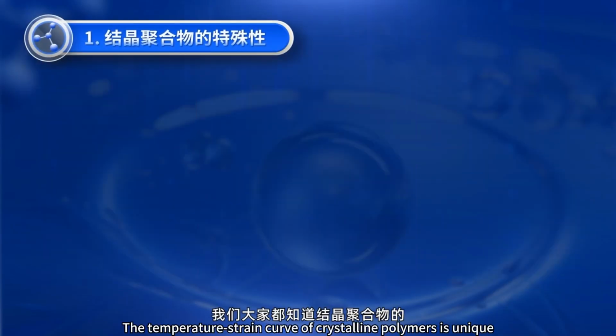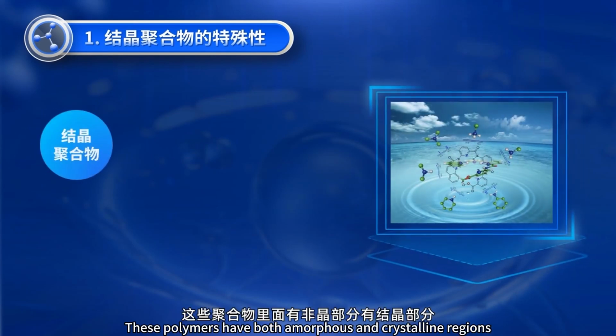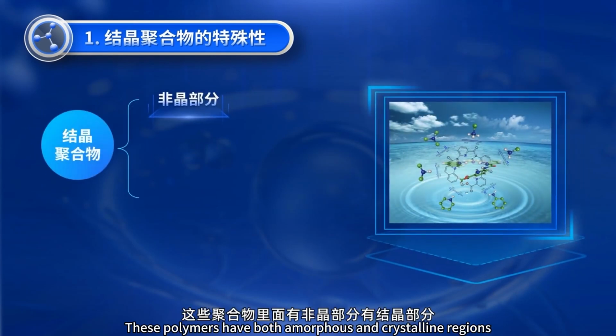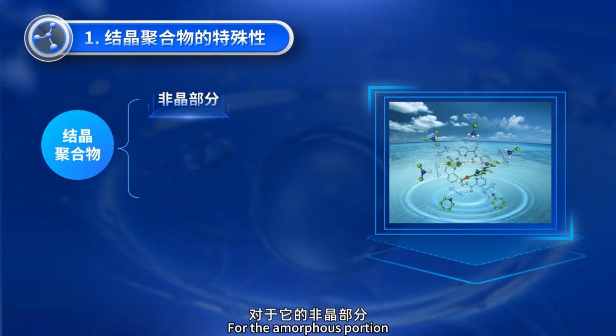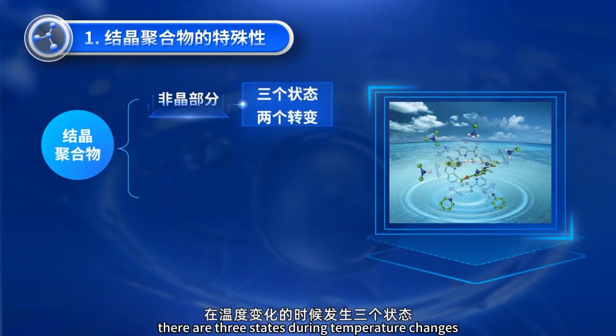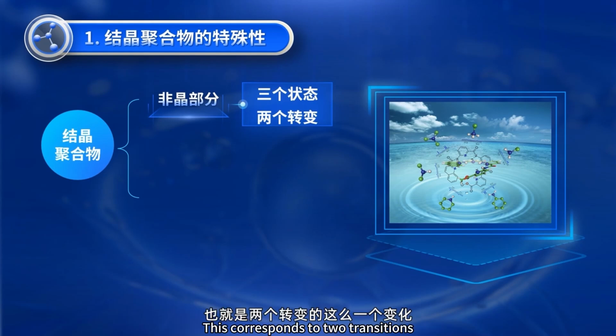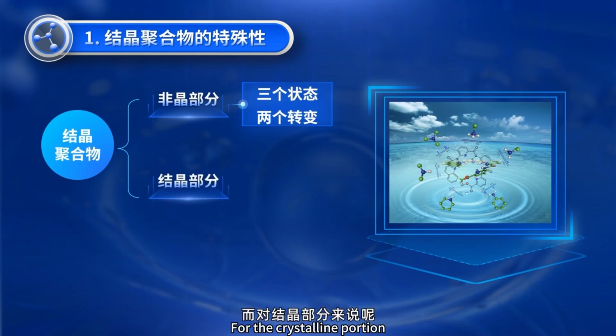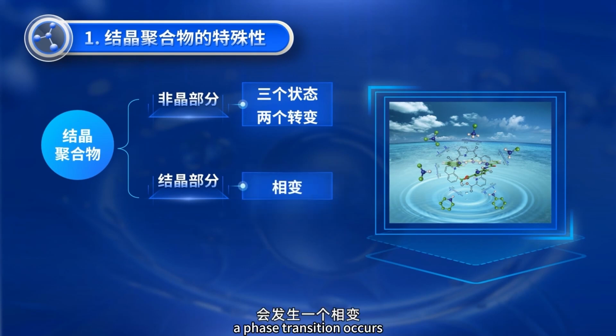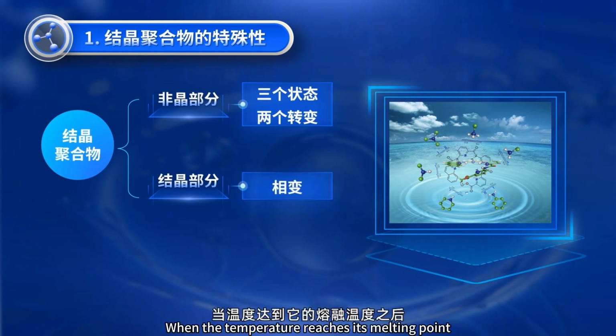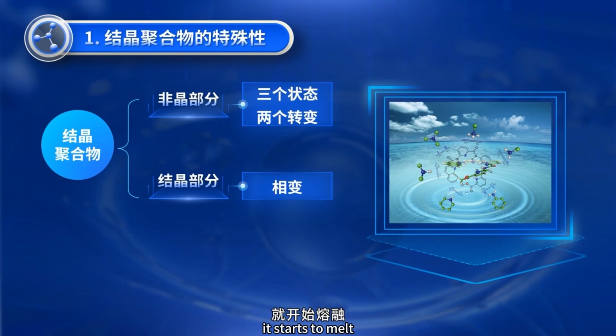As we all know, the temperature strain curve of crystalline polymers is unique. These polymers have both amorphous and crystalline regions. For the amorphous portion, there are 3 states during temperature changes. This corresponds to 2 transitions. For the crystalline portion, as the temperature increases, a phase transition occurs. When the temperature reaches its melting point, it starts to melt.